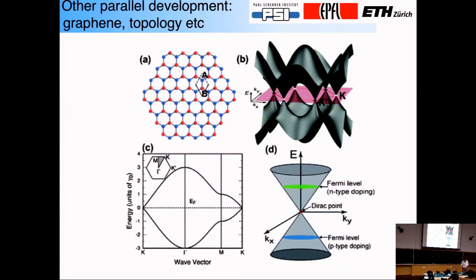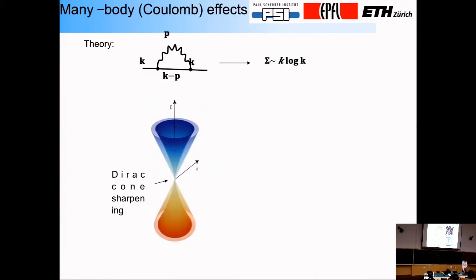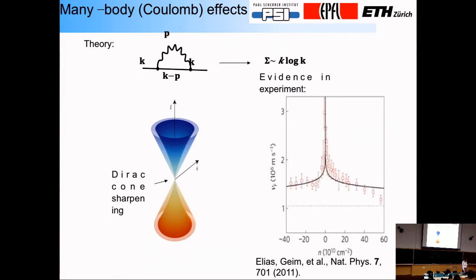But this is just in the one electron part. Actually, the electron-electron interactions here give some non-trivial results. I'm not going to derive these for you, but they preserve these cones, but actually the cone is converted into an hourglass. So when you add that U term here, in this case you have to be careful. You have a U term, but then you have to take care of the further range interactions as well, because screening is not so good. But when you add the Coulomb interactions, there's something qualitatively new that happens.